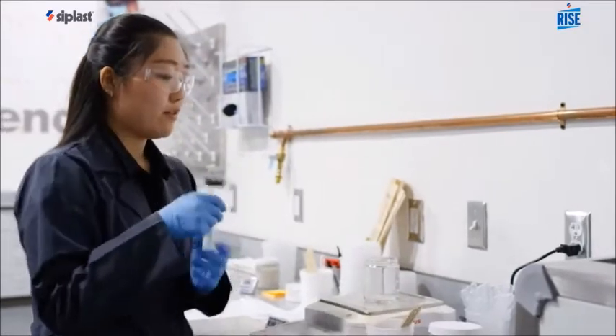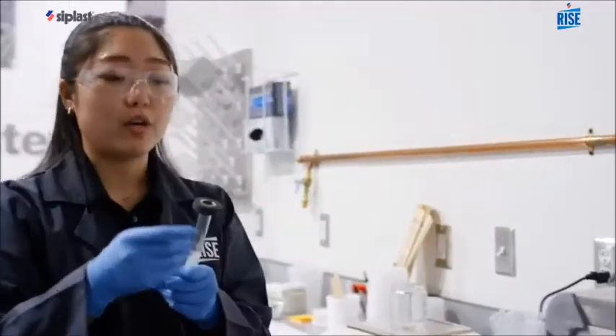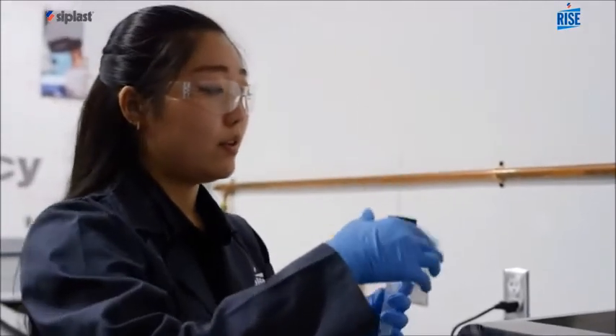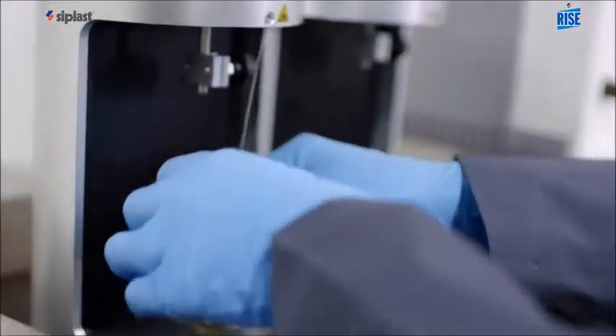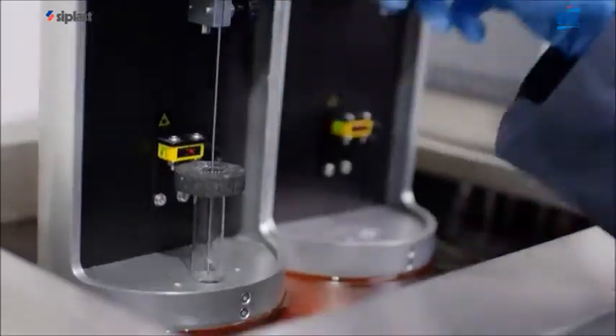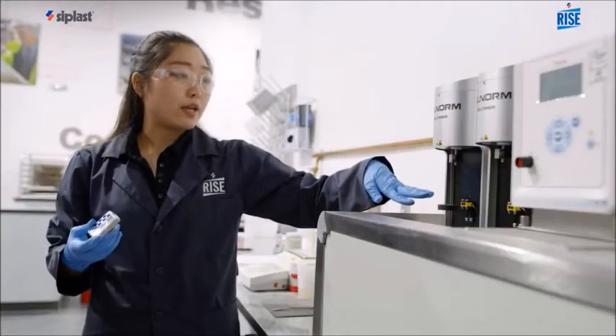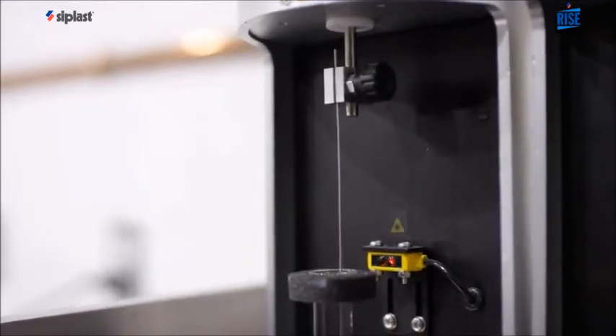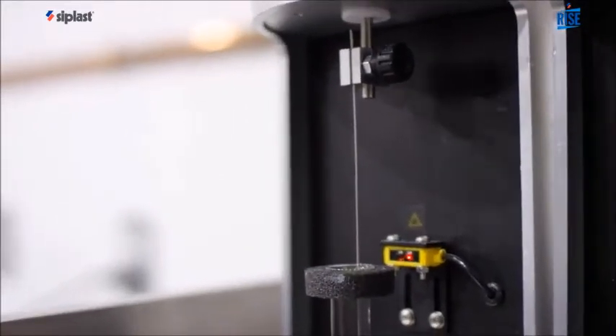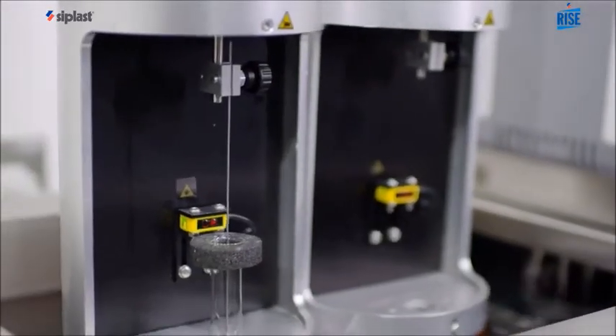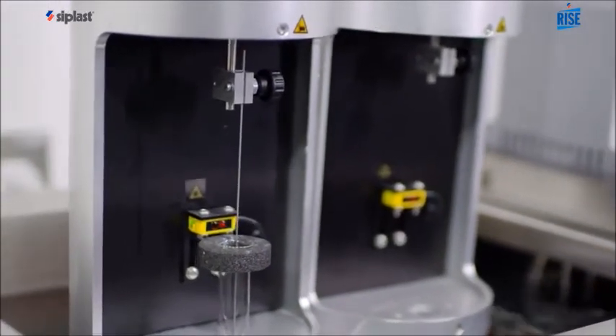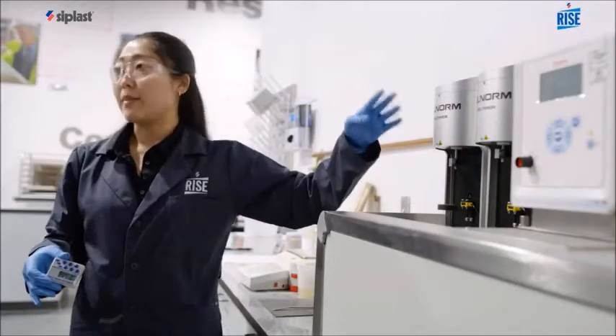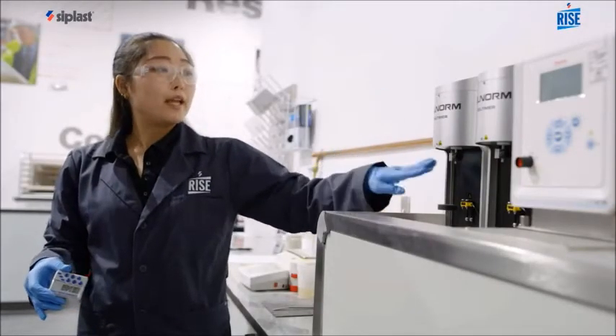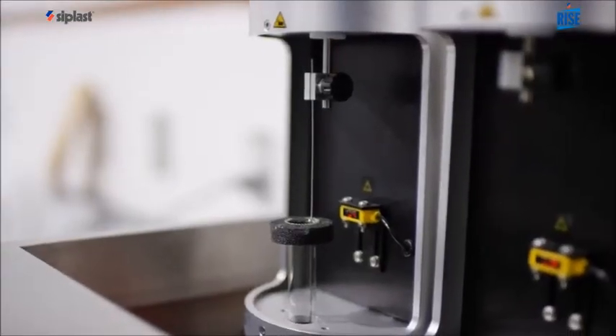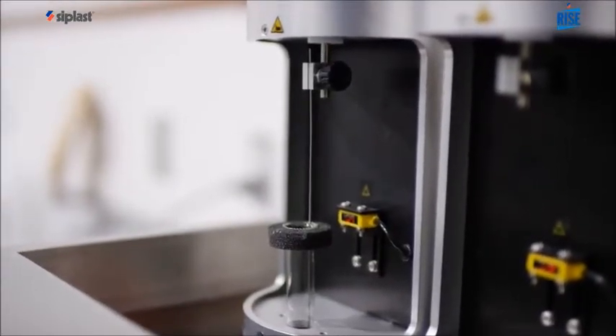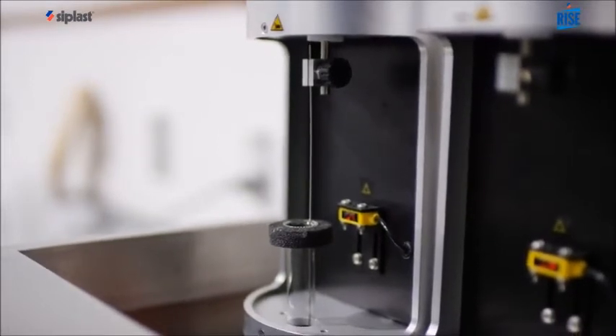And once I have enough, it really depends on the product and how much you put on, but it's basically a little bit above the water line. And I'll put it in the unit, make sure the stamper is clamped on. Basically what it's doing right now is we have our resin in the test tube underneath mixed with the catalyst, so it starts catalyzing, curing, polymerizing. And the stamper on the top is just moving in an up and down motion, making sure it's getting mixed at a constant speed. And once the gelation happens, the stamper gets stuck in the resin and pulls up the test tube, blocks the light, and therefore stops the timer.